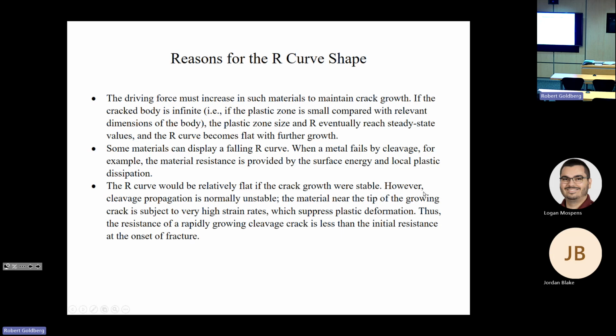When a material fails by cleavage, for example, the material resistance is provided by the surface energy and the local plastic dissipation. So if crack growth were just stable, the R curve would be relatively flat. However, cleavage propagation is normally unstable. The material near the tip of the growing crack is subject to very high strain rates, which suppress plastic deformation. And the resistance of this rapidly growing cleavage crack is less than the initial resistance at the onset of fracture.